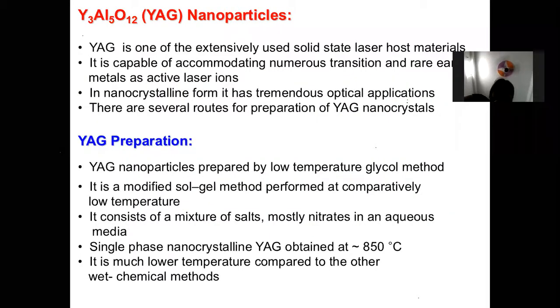Second, this is the YAG nanoparticle. Most of this work was done by Nanda, who is sitting there. She has done it at RRCAT. YAG is one of the extensively used solid state laser materials. It is a very useful solid state host material, and most of the lasers in the IR region are made with this material. It is so important, but making a single crystal of this material is very, very expensive, because the melting point of YAG is around 2000 degrees Celsius. YAG is basically yttrium aluminum garnet.